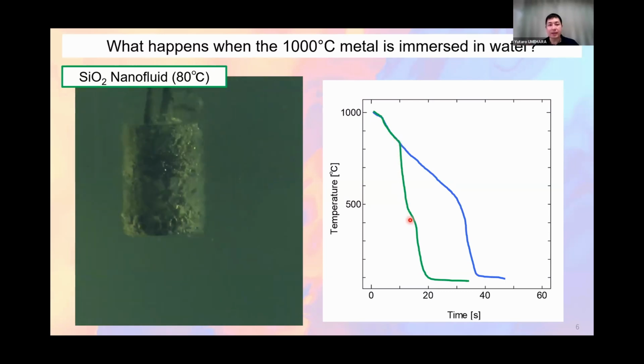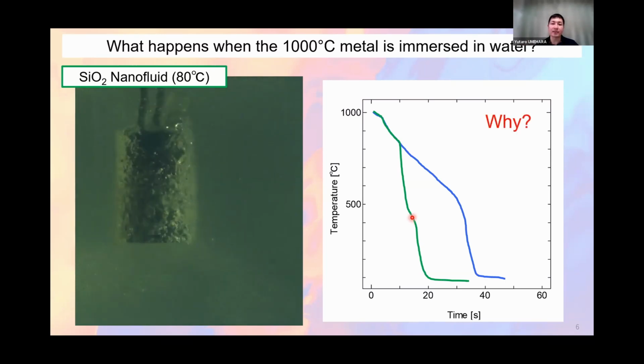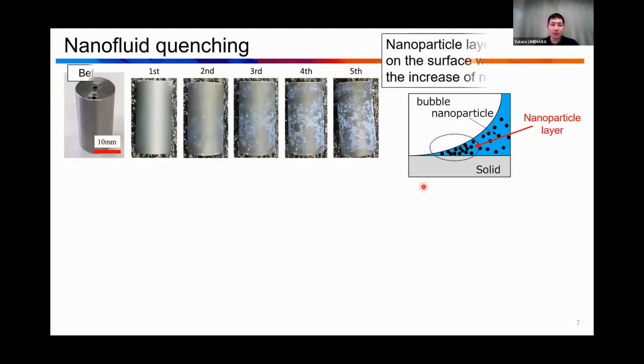the cooling rate is enhanced. So this is a research question: why does this phenomenon occur in a nanofluid? The reason is surface conditioning. Before the quenching starts, it is like this stainless steel rod, but when we repeated the test, heating up and cooling down, and heating up and cooling down repeatedly, the surface condition also changed.